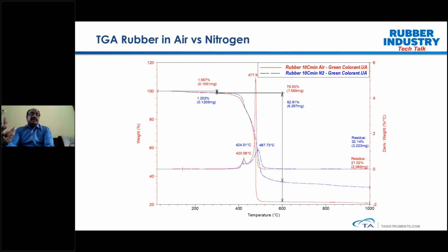So what this signifies is that furnace control is very, very important, and that's where we need to be very careful in selecting the TGA, how well the furnace is going to control the atmosphere. And also the gas switching needs to be very fast and efficient. So this particular analysis shows how well the atmospheric condition, either air or nitrogen, is going to have an impact on the decomposition kinetics.